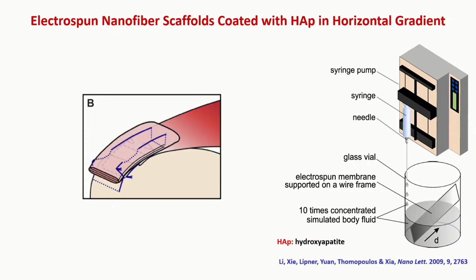And by adding this solution drop-wise, the liquid level, of course, will increase gradually from bottom to top. So you can imagine the region at the bottom will have a longer deposition time than the region at the top of the scaffold. So naturally, you are going to build a gradient along this vertical direction. So that's basically the setup. As you can see over here, you have some scaffolding materials put on a glass substrate, and then you add the solution from the top, and then you're going to build a gradient.